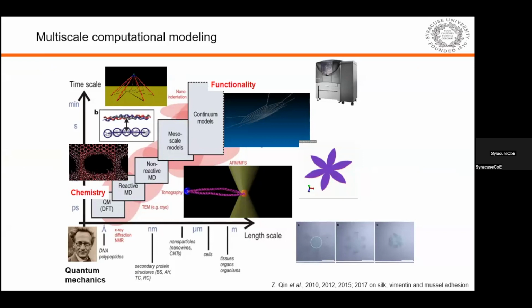Here is a schematic figure summarizing how multiscale modeling is defined. We can scale from the most fundamental scale levels, below angstrom, where we study how atoms and electrons interact with quantum mechanics, modeled by DFT simulations. Using that, we can generate force fields for classical MD and reactive MD simulation. Based on that, we can do coarse-grain modeling. We can apply it to mesoscale studies to study how the different material phases interact and contribute to the mechanics of the composite. And then we can generate continuum-scale constitutive laws for large-scale simulation.